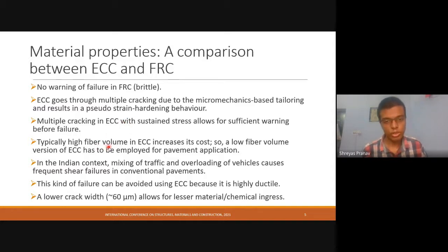But then ECC also requires a high amount of fibers. One of the major reasons for this behavior is the high fiber content, which is close to 2% by volume fraction of PVA fiber. So that causes the cost to increase a lot. So for the Indian context, a low fiber volume version of ECC has to be employed for pavement applications, so that the guidelines are satisfied and also the tensile ductility behavior is retained. And specifically for the Indian context, we have a huge amount of traffic volume, and there is a lot of intermixing of heavy traffic and light traffic, and it causes a lot of failures in the conventional pavements. And having high tensile ductility can help neutralize a lot of those stresses in the pavements.